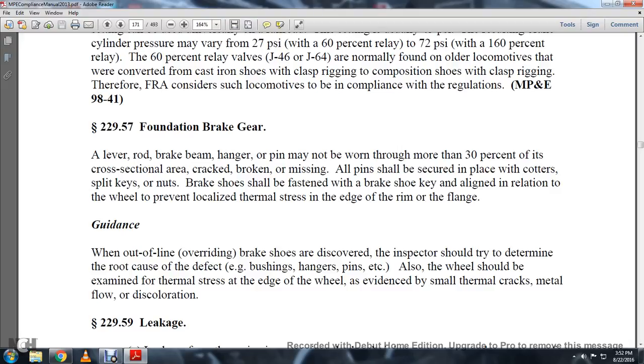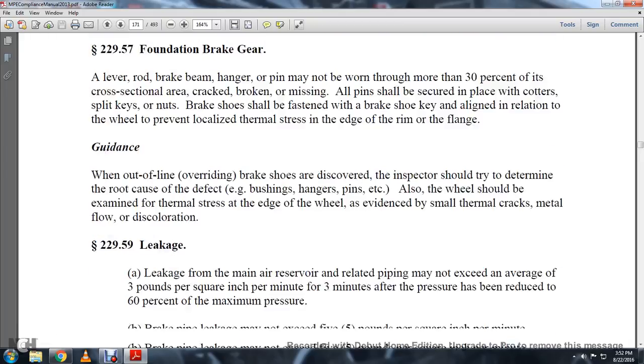Guidance. When an out-of-line or overriding brake shoe is discovered, the inspector should try to determine the root cause of the defect, such as the bushings, hangers, and pins. Also, the wheel should be examined for thermal stress at the edge of the wheel, evidence of small thermal cracks, metal flow, and discoloration.